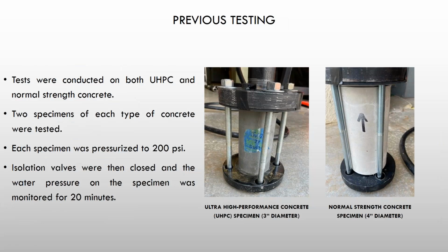In previous testing, the tests were conducted on both UHPC and normal strength concrete. 2 specimens of each type of concrete were tested. Each specimen was pressurized at 200 psi, and then the isolation valves were closed, and the water pressure in the specimen was monitored for 20 minutes. Here you can see a 3-inch diameter cylinder of UHPC and a 4-inch diameter cylinder of normal strength concrete.